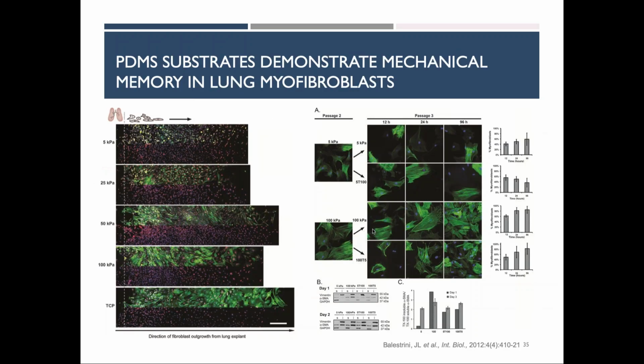Another demonstration of PDMS being used in pulmonary engineering has shown us that mechanical memory exists in lung myofibroblasts. So these are fibroblasts that they've grown on different stiffnesses of materials, and if they start out growing them on a very stiff material, 100 kilopascals, and then put them on either a stiff or soft material, they see that this mechanical memory, this activation in the cells where you see enhanced alpha smooth muscle actin expression and organization, is persistent even when these cells are plated onto a soft material later. So it's been a very powerful way to study how these cells are responding and how we could potentially reverse disease. Obviously, it's complicated because of this mechanical memory in the cells. It also reminds us that if we're growing our cells on tissue culture polystyrene or regular Petri dishes, it's important to think about how we have pre-programmed our cells before we test them in our own biomaterials.